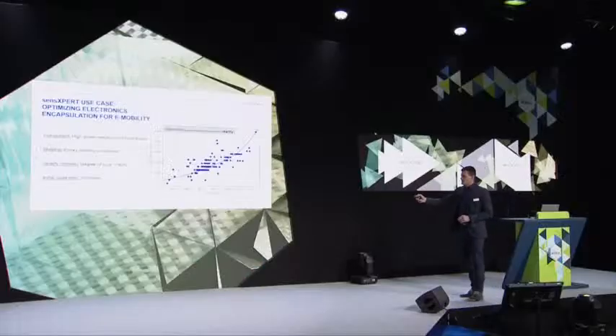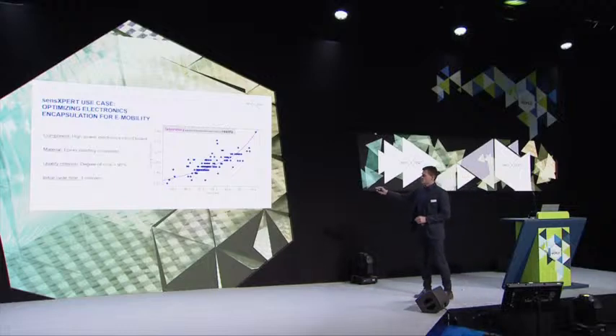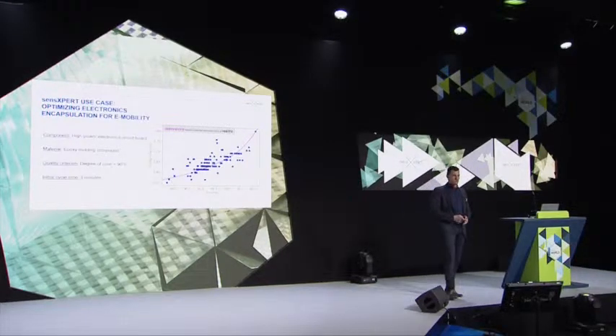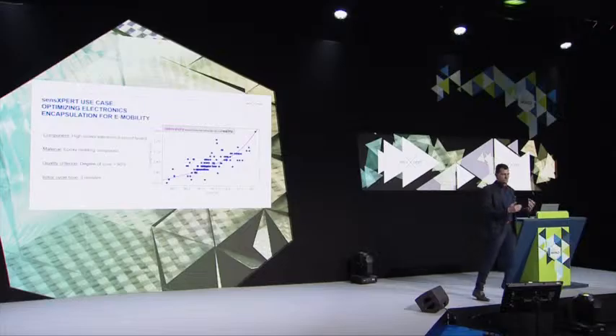But what you can clearly see here on this picture is the blue dots is the real material behavior in a series production environment. Here you can see an excerpt of 50 parts that have been characterized here and monitored. And the purple line, this is what you would expect if you characterize the material from one batch in the lab and you try to predict the process behavior of the material. And you can clearly see, yes, there is a trend, and it follows this trend, but we have a huge deviation in there.